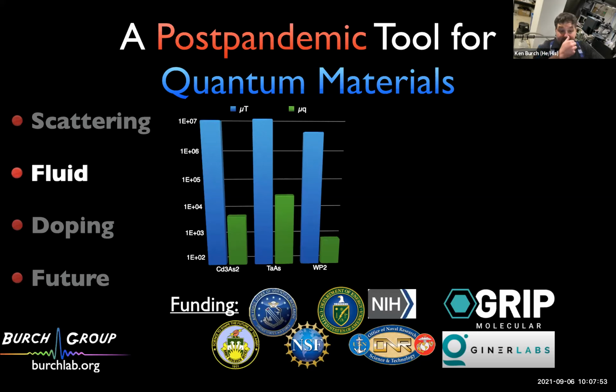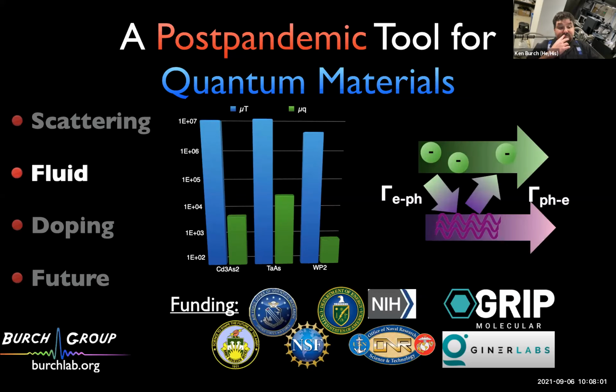As I will show you, we now have direct evidence from Raman that the phonons strongly couple back into the electrons. Normally when you try to do transport, electrons can scatter into phonons, phonons scatter into other phonons, and you lose the energy and momentum. That's basically where it goes into heat. But if you have the case like we have here, where the phonon-electron scattering is strong, that momentum is actually mostly recovered by the electron bath. As a result, you have a strongly coupled electron-phonon fluid, which can then carry the energy and momenta and give you these very long apparent transport lifetimes, even though your single particle scattering rate is of course much, much higher.